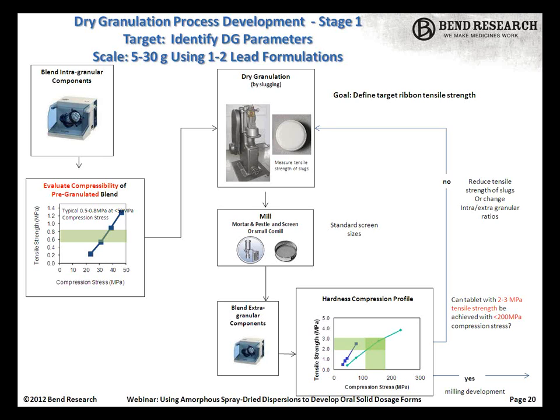So at this point, we've identified, and of course, if this is a direct compression, we're just doing a standard compression profile, which would be on the bottom right-hand curve here. And as I mentioned, we very rarely have issues with this, but we still generate this because it gives us our guidance for the roller compaction settings to achieve the desired ribbon. Of course, what we found is that we actually have a very good agreement of being able to scale from these slugs to ribbons using the solid fraction technique.